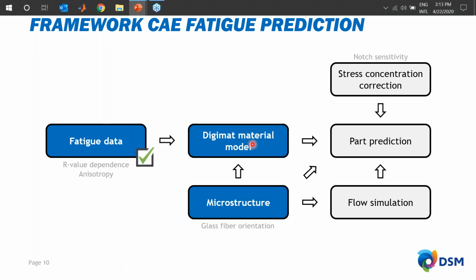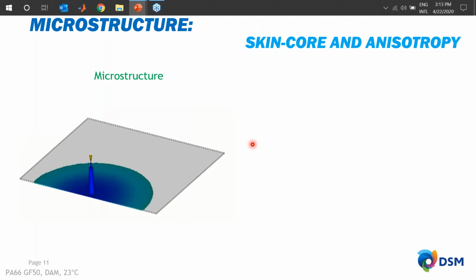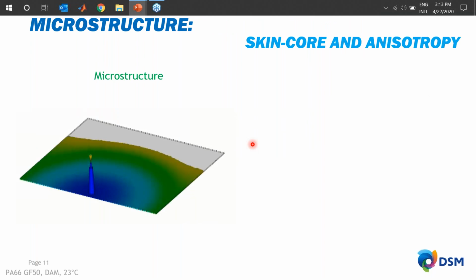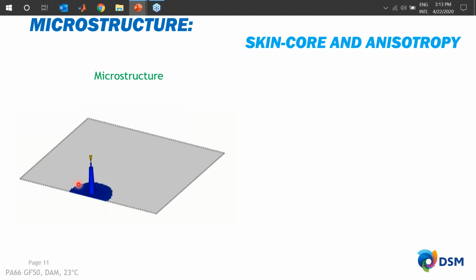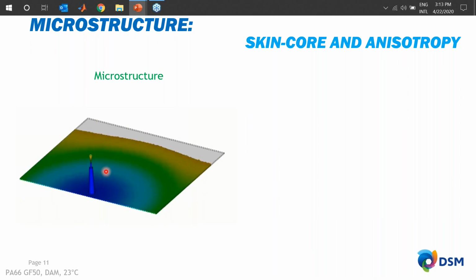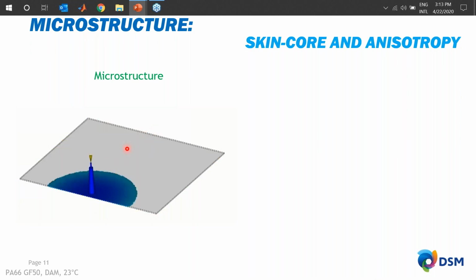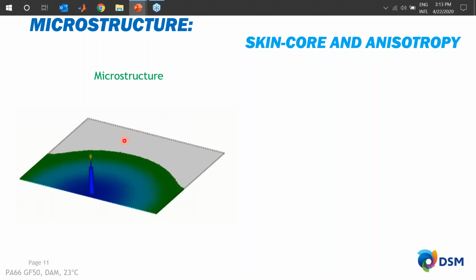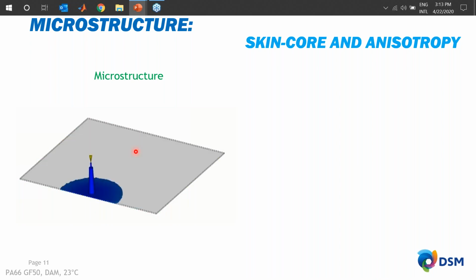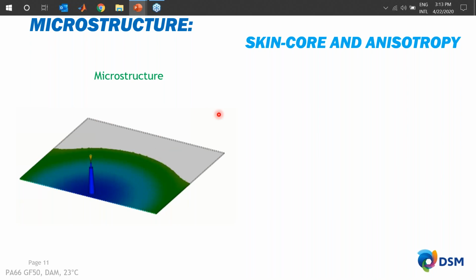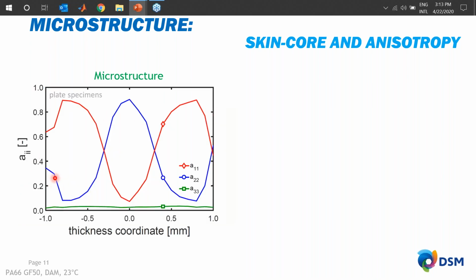So first, before we can go to the material model, you have to understand what the microstructure of this plaque looks like. Because since this plaque is injection molded, you can see initially you already have some kind of biaxial stretching in the beginning. And in the end, you have the shear flow because of filling the remainder of the plaque. So as a result, you can imagine that at the edges, you have highly oriented fibers because of this flow. And in the middle, you have more or less perpendicular oriented fibers to the flow because of the biaxial stretching.